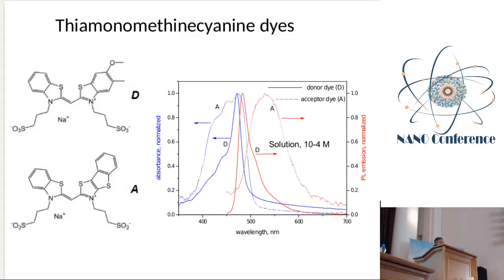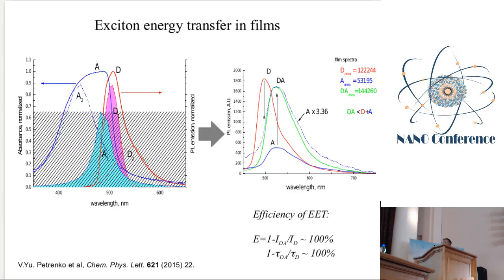We studied two specific molecules, thiamonomethinecyanine dyes, which have a similar structure and which differ by only end groups. And this specific structure provides that the optical properties, absorption and photoluminescence spectra of these species are very close, as shown here. For example, the emission of the donor molecule overlaps very well with the absorption of the acceptor. In films we compared photoluminescence properties of the films prepared from the neat components and from the mixture of donor and acceptor aggregates.